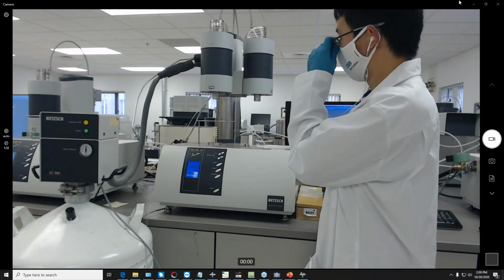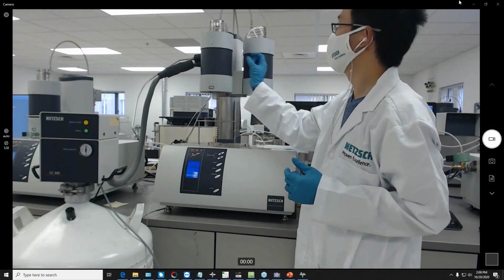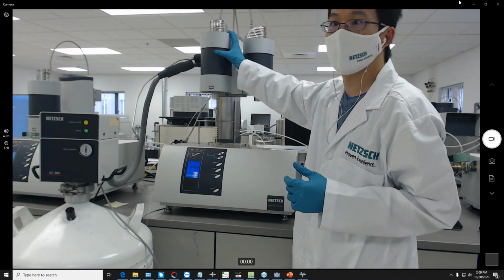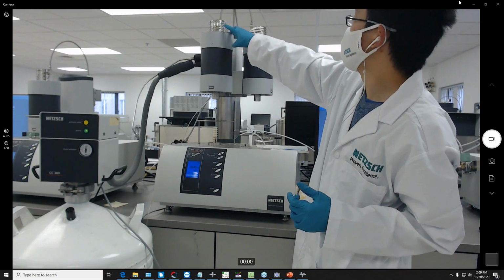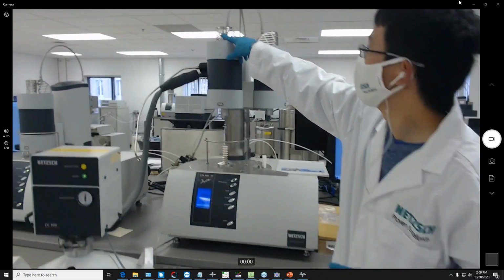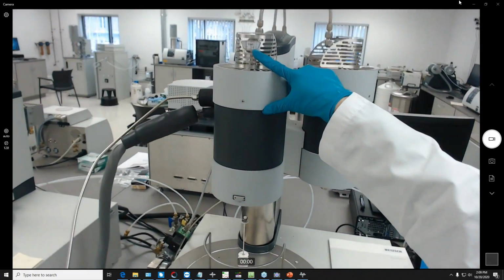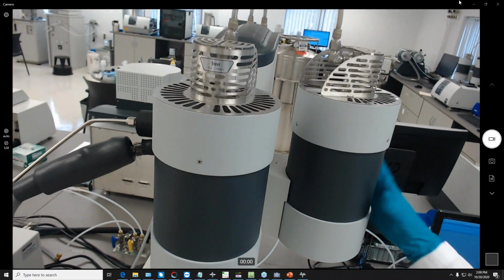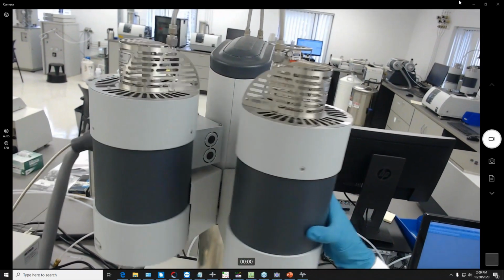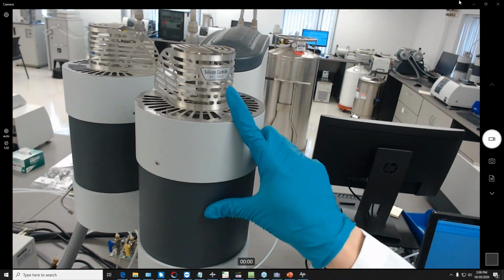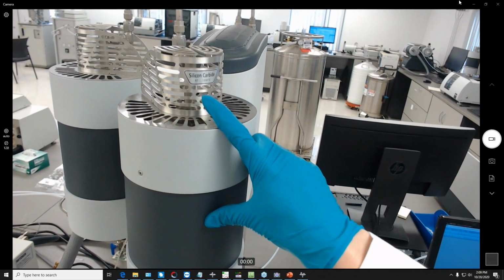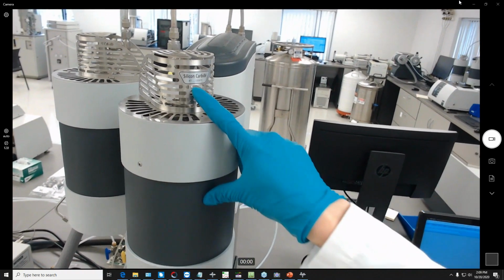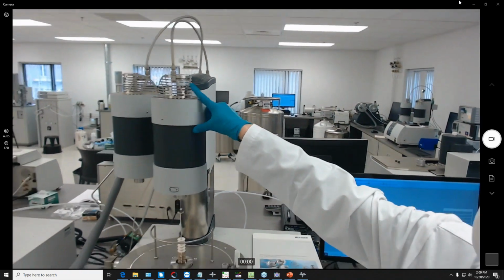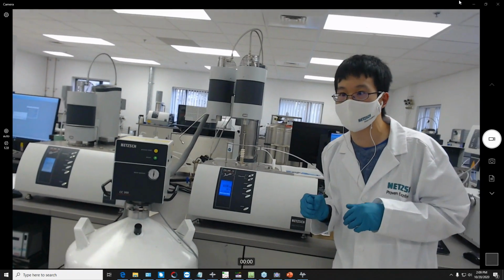ideal temperature ranges. So as an example, on my left furnace here, I have a steel furnace. So the range of the steel is from -150 Celsius all the way to 1,000. And then if I switch over to my right furnace, which is a silicon carbide, I can have a higher end top temperature range. So this one will run from room temperature to 1550 Celsius.